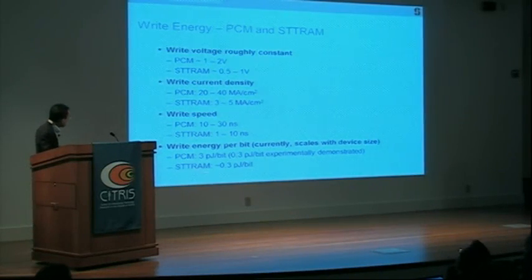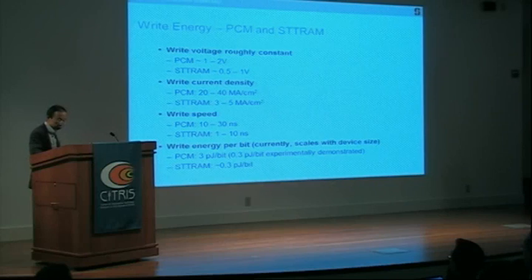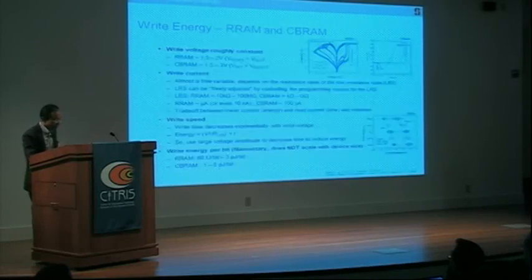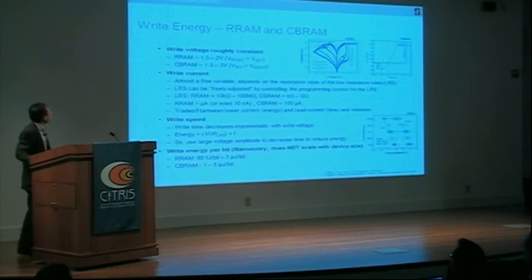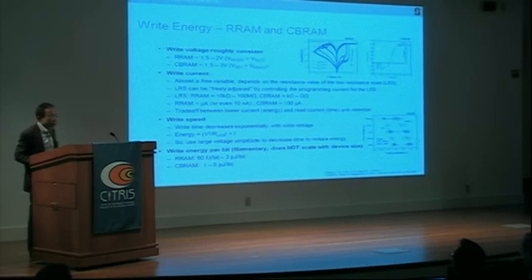Of course, as you scale down to smaller and smaller sizes, these will go down. For example, we have done some experiments to scale down the area of the bottom electrode quite substantially, and we were able to experimentally measure 0.3 picojoules per bit. So scaling down is possible. All right, now the write energy for this filamentary conduction, like RRAM and CBRAM, is a little bit more complicated. There's a lot more nuance to it.